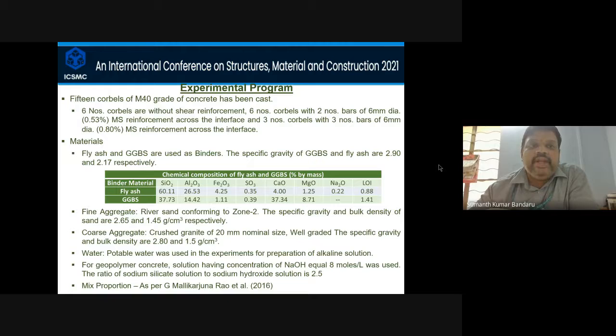Coming to my experimental program, we have cast around 15 corbels with M40 grade: 6 corbels with no shear reinforcement, 6 corbels with 2 bars, that is 0.53% of reinforcement crossing the interface, and 3 corbels with 3 bars of 6 mm diameter, that is 0.8% of reinforcement crossing the interface.